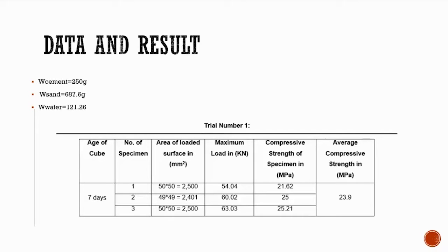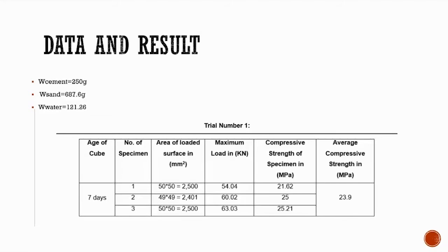Data and results. The amount of cement is 250 grams, sand is 687.6 grams, and water is 121.26. Age of cube is 7 days. Number of specimens is 1, 2, and 3. Area of loaded surface in millimeters squared. In trial number 1, specimen 1 is 50 by 50, which equals 2,500, and its maximum load is 54.04 kN. Compressive strength of the specimen is 21.62.